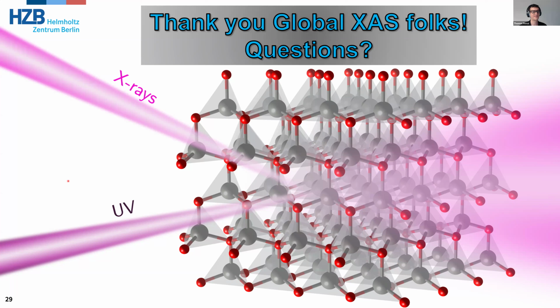I have two questions that build off of each other. I was wondering how big your nickel oxide nanoparticles were, and then if you have any quantification of how many excitons you're producing per pump of these nickel oxide nanoparticles. Okay, so the first question, the nickel oxide particles typically have a diameter of a micron. So these are microcrystals in suspension. They really have a bulk structure. And we had to tune the pump wavelength to just the onset of the charge transfer gap, because otherwise the penetration depth was not deep enough, and we were getting a mismatch between pump and probe penetration depths.